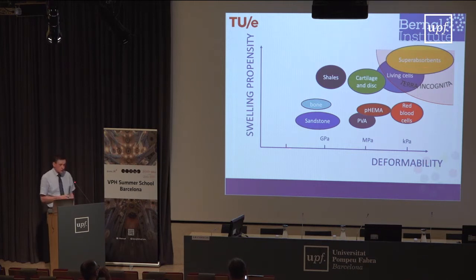you can draw many different applications in terms of the stiffness of the material and in terms of its swelling propensity. And then you see, for instance, sandstone is something very stiff and not swelling at all. If you go down to gels, then you have PVA, which is somewhat swelling, but not so much. HEMA may be a little bit more. And you may have ionized gels, which are much more up in the corner there. But cartilage and disc are somewhat swelling and in the order of megapascal stiffness. But if you talk about intracellular space, you're up to kilopascal stiffness and very high swelling propensity.